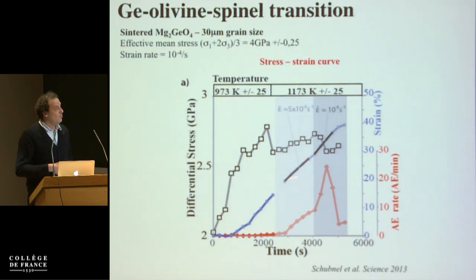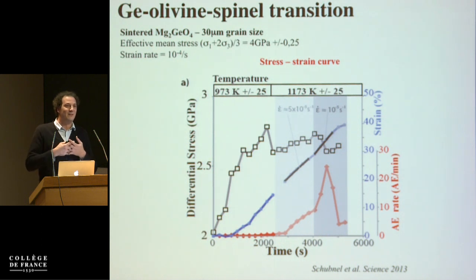And so this is the one experiment that we did on the pure magnesium germanate olivine. So we're at 4 GPa. The strain rate is 10 to the minus 4. This is the differential stress as a function of time. And in blue here you have the strain, and you see you build up the stress, you're at 700 degrees and nothing happens, and then a very counterintuitive phenomenon happens when you increase the temperature. Any material, when you increase the temperature, you would expect it to become more ductile, and suddenly, as you increase the temperature by 200 degrees here, you have suddenly hundreds and hundreds of acoustic emissions, and really the sample behaves as if it was pure glass.